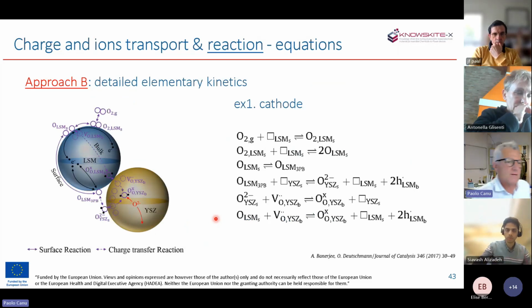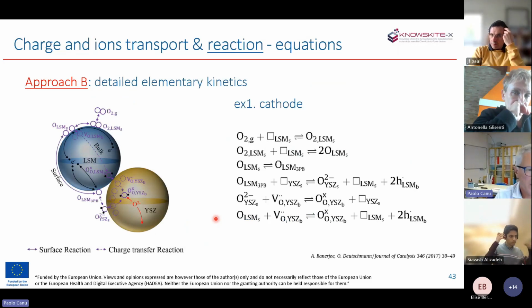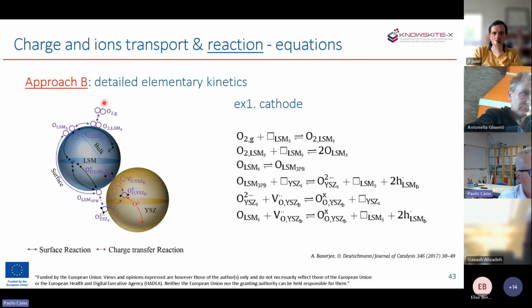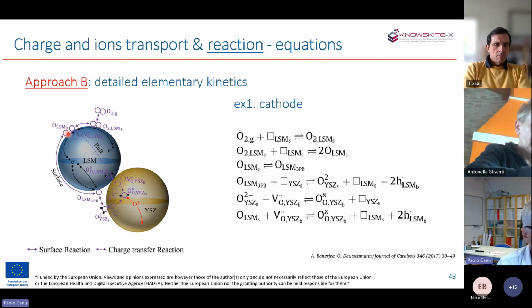These are some examples. That's one example of a detailed mechanism on the cathode side, where the oxygen as a gas is assumed to adsorb molecularly on the electronic conductor, then split into adsorbed oxygen, diffuse on the surface up to the three-phase boundaries, and then combine with surface sites and later vacancies on the ionic conductor to finally determine the flux of ions within the ionic conductor.